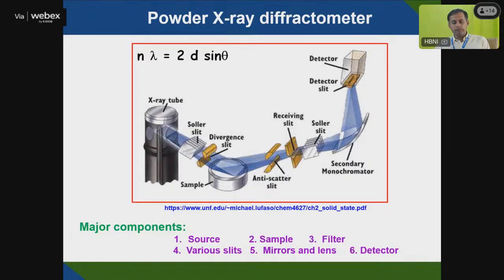Now if you see the powder diffraction method, this is a schematic of an X-ray diffractometer. You have a sample holder here, where you're keeping your sample. Then you have the X-ray tube. From the X-ray tube you are getting the X-ray, which falls on the sample surface. Then you have slits, divergent slits and Soller slits. After passing through the different slits, it will fall on the secondary monochromator, from which it will go to the detector. The detector will identify those peaks and give you the diffraction pattern. So you have a source, a sample, a filter, then various slits, mirrors, and a detector.